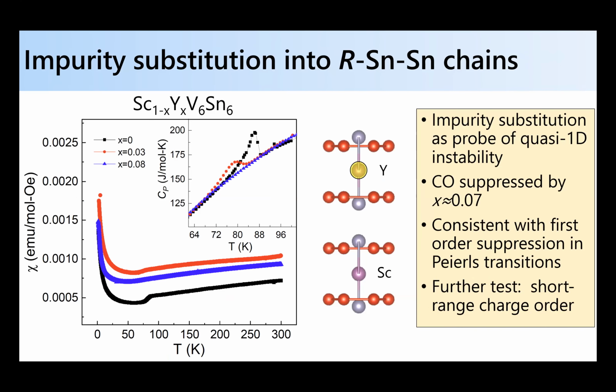Okay, so if you want to test it using materials, we can alloy the system a little bit. You can place a little bit of scandium with a little bit of yttrium, which is bigger, and you can introduce disorder along these chains. And if it's a 1D instability, it should be extremely sensitive to disorder. And indeed, charge order is completely suppressed by the time you put 7% yttrium onto the scandium sites. Okay, and that's just a susceptibility showing you charge order is present in the parent, damped by 3% and gone by 8%.